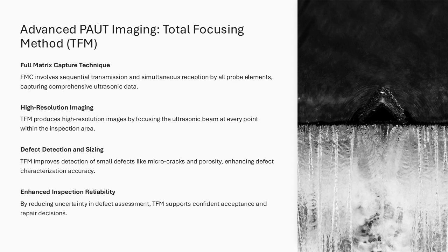radiographic quality. For stainless steel cladding, TFM is particularly valuable because it enhances signal clarity and defect definition in highly anisotropic materials. This improved resolution allows for accurate detection and sizing of small, complex defects such as microcracks, clustered porosity, and irregular disbonding. From an engineering reliability perspective, TFM reduces uncertainty in defect characterization and improves confidence in acceptance or repair decisions. While TFM typically requires more computational power and careful setup compared to standard PAUT, its benefits in critical applications often justify its use.